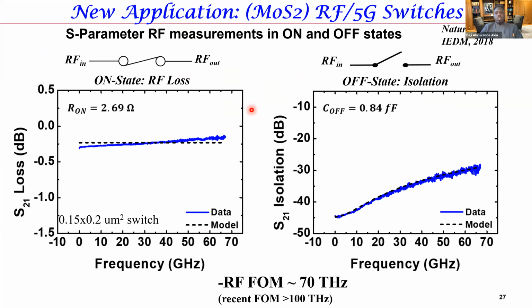I won't spend too much time, because these are more specialist data, but those that do radio frequency measurements will be familiar with these so-called scattering parameters, which is just a measurement of the loss. If you had a perfect transmission line, it's going to be 0 dB as a function of frequency. In this particular device, in the on state, it's very close to 0 dB - anything better than negative 0.5 is actually very good.